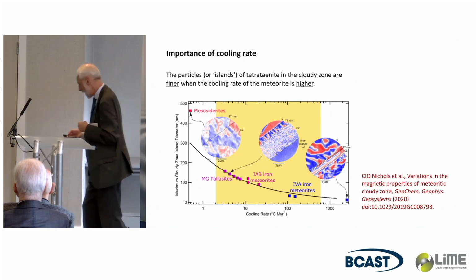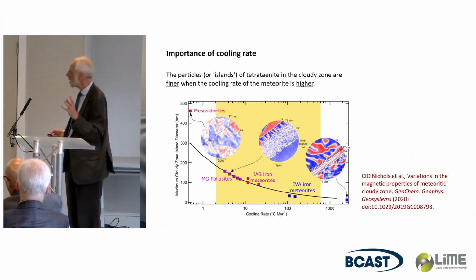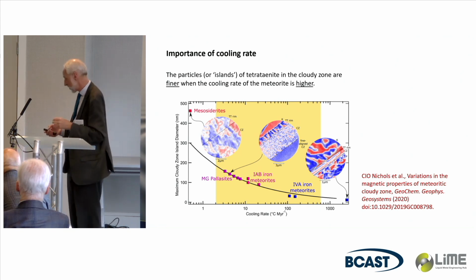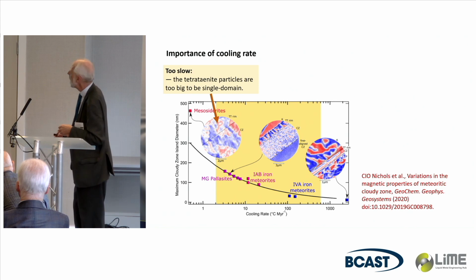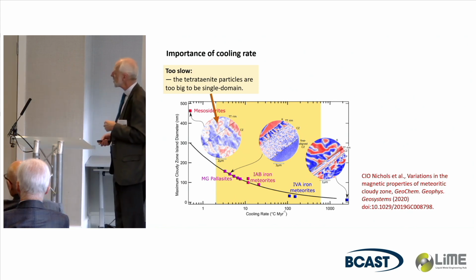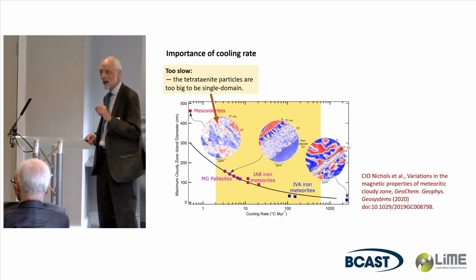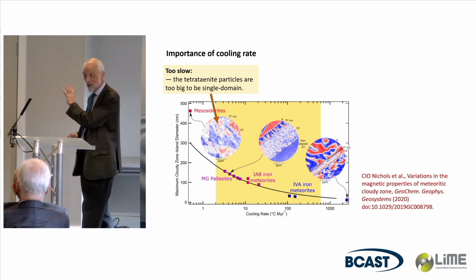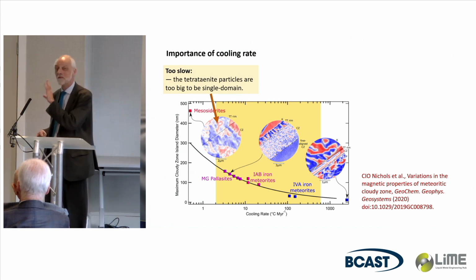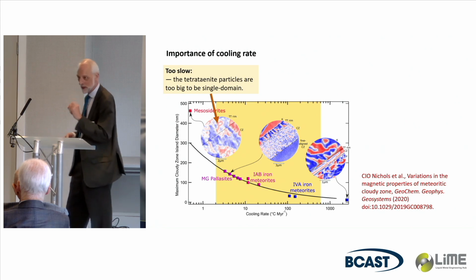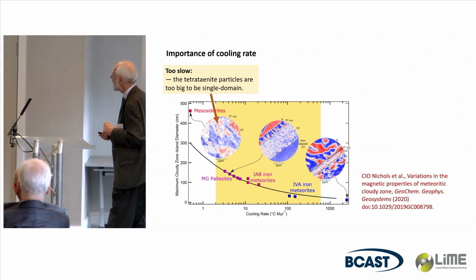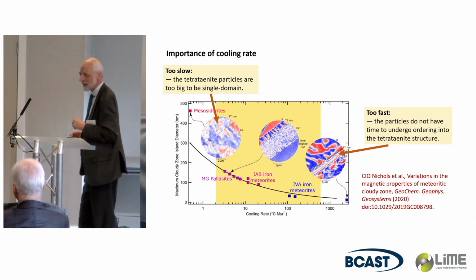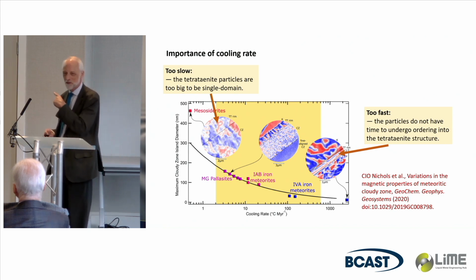Why? Well, if you take meteorites that cool at different rates, or regions that cool at different rates, if it cools too slowly, the tetrataenite particles are a bit big, and they therefore are not magnetic single domains, and that single domain particle size is critical to get the best performance. If your cooling is too fast, they don't have time to form the tetrataenite.